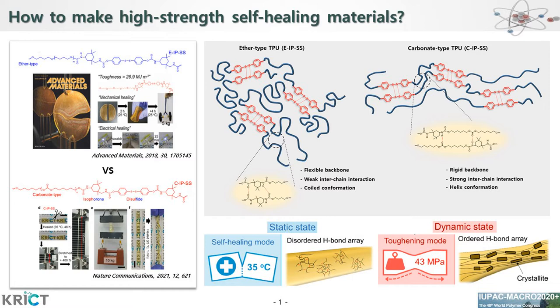Why is there such a difference? Unlike ether types, carbonate polyols have a rigid backbone and strong inter-chain interaction, so the ether type has a coil shape and the carbonate has a helix shape. Under strain, the amorphous phase of CIPSS is transformed into a rigid metastable crystal where ordered hydrogen bonds form between stretched chains to endure heavy loads. After removal of the stress, the metastable crystal returns to the amorphous phase, which is shape and strain fully recovered, and this elastomer is immediately available for self-healing.